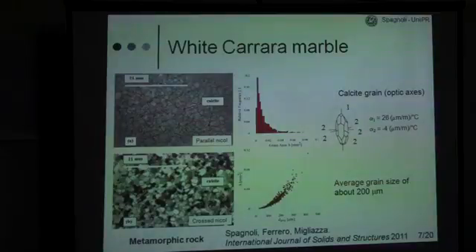So white marble is a metamorphic rock, and at the microstructure level it is characterized by grains of calcite. And here on the left you can see two pictures. The one below is obtained with polarized light, and in this way you can detect the orientation of the grains. You have a distribution of the grain size, and the average on the specific marble that we investigated is about 200 microns.